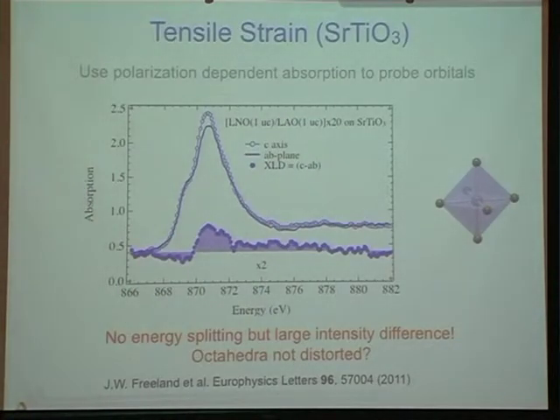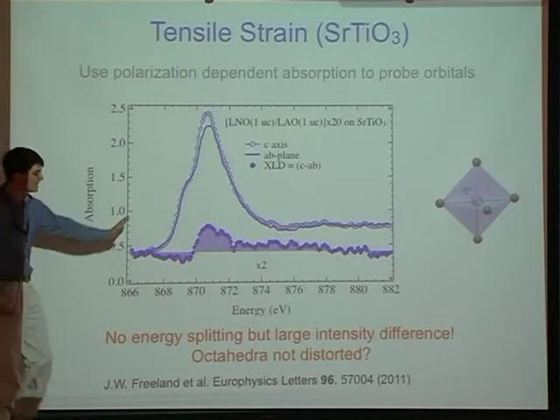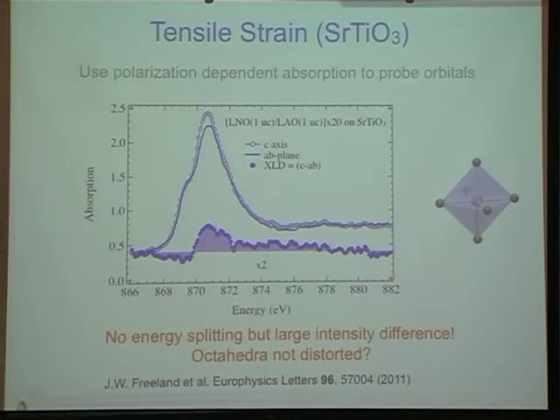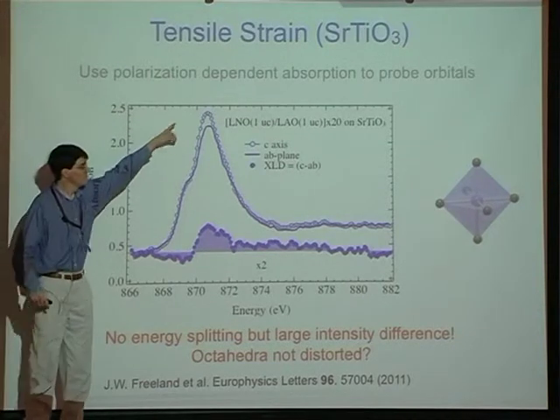And we did the same experiment in heterostructures because the goal was to really use a heterostructure to cause orbital polarization. So now I'm showing you a lanthanum nickelate, lanthanum aluminate heterostructure where I have 1 unit cell of each material. And again, this is this spectroscopy where I'm measuring this nickel L edge. I'm varying the polarization. And I find 2 very strange things. In lanthanum nickelate as a single film, there was no orbital polarization. Now I'm seeing a difference in intensity here.